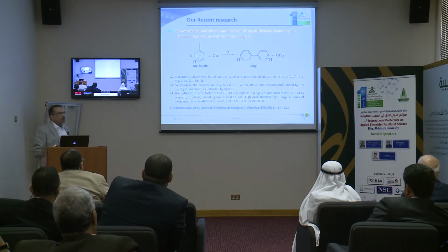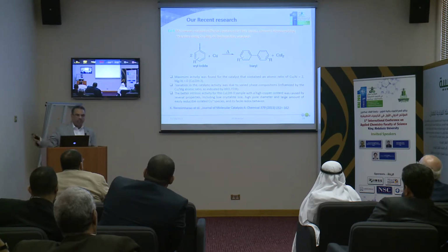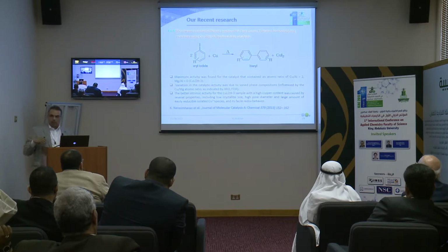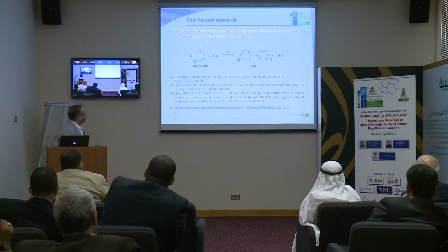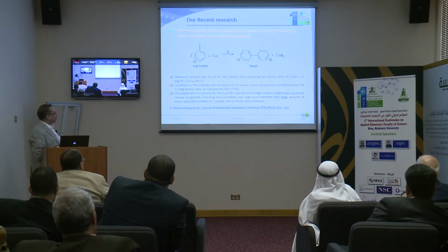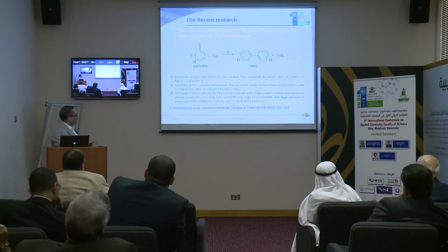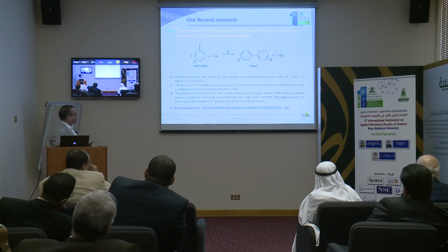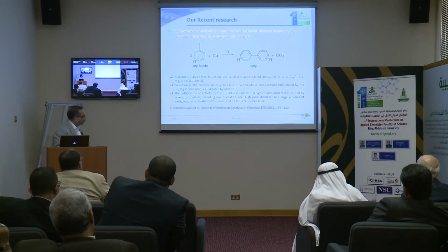So what if we introduce the copper itself in the cationic sheet, and we already have the basic properties of the material? So we can have the copper in the cationic sheet, and we have the basic properties of the material itself. So we can use it as one and only one catalyst for the synthesis of the CC coupling. We tried this work, and we found that by isomorphous substitution of the divalent magnesium from the cationic sheet by copper, we succeeded in getting the best catalyst for the synthesis of the CC coupling